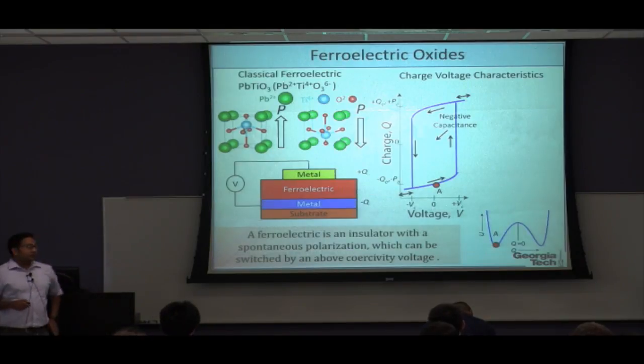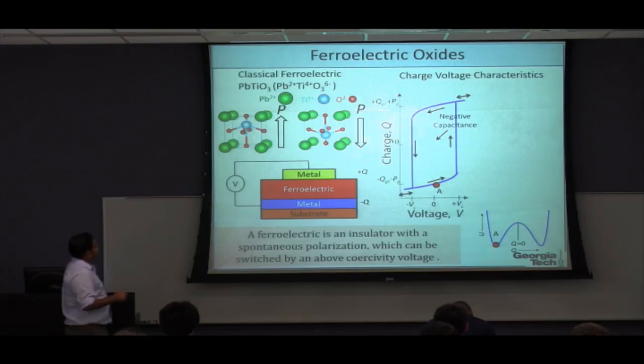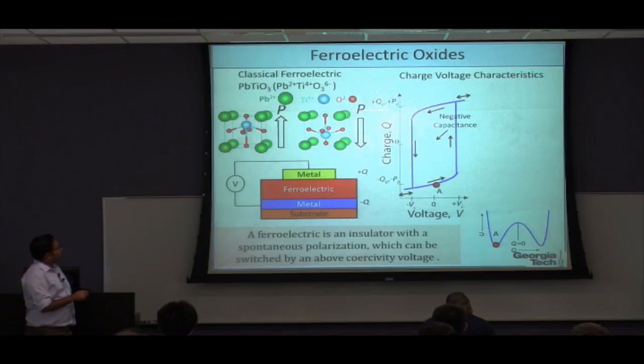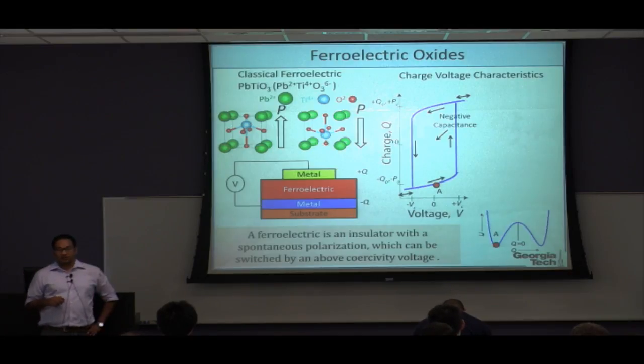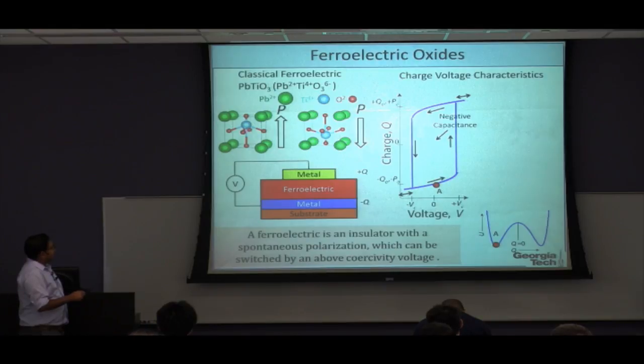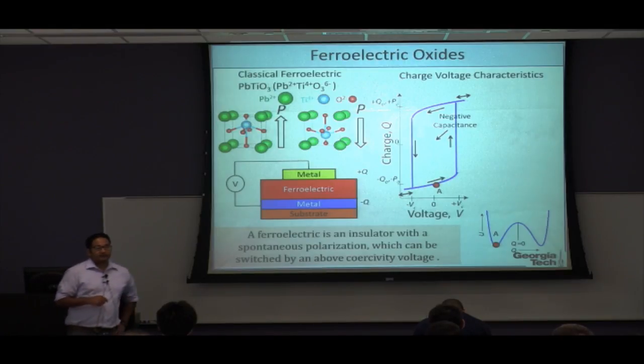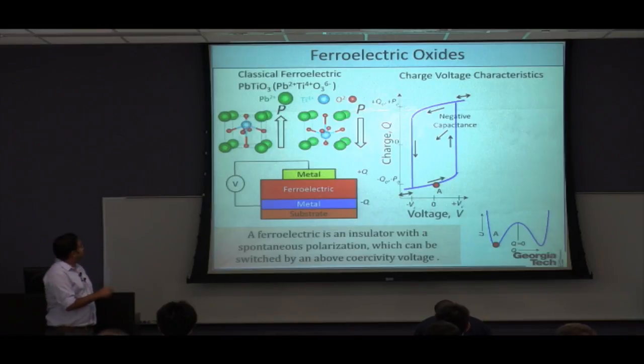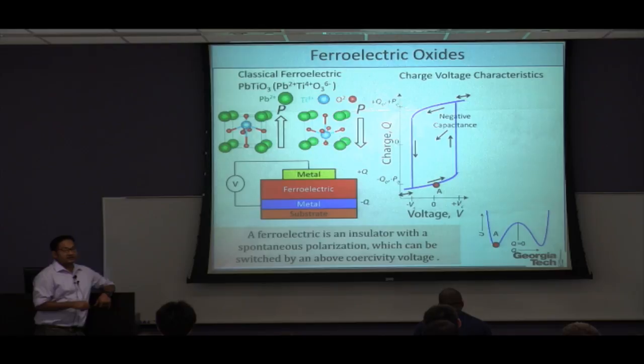So a little bit of background on ferroelectric materials. Ferroelectric materials are crystalline materials whose unit cell looks like this. If you look at the unit cell, you'll see that the central atom is not at the center of symmetry of the material. Rather, it's slightly off-centered, and this slight off-centering of the atom gives rise to a built-in spontaneous polarization, which means that if you plot the charge-voltage characteristics of a ferroelectric material, there will be a hysteresis. The minima of this energy landscape correspond to the two directions of the polarization.